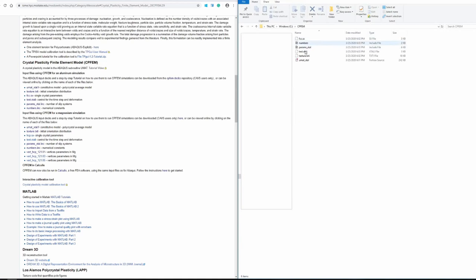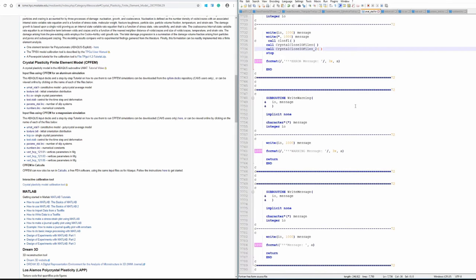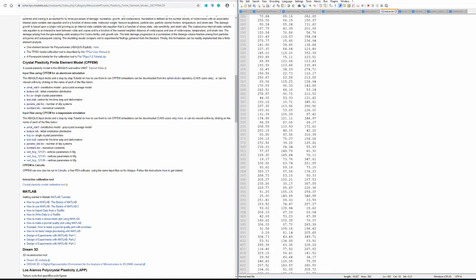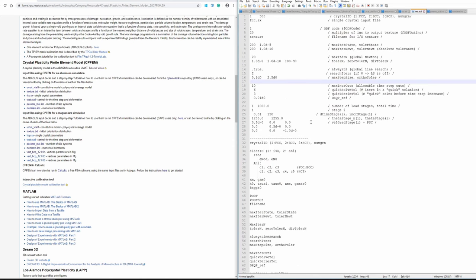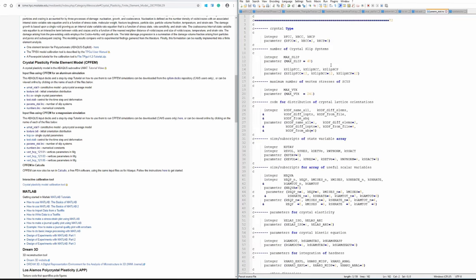Now we have all six files. Let me explain briefly what they are. This .for file is the UMAT—a very huge file with seven thousand lines. The texture file consists of Euler angles for different grain orientations. There are 500 grains and 500 pairs of Euler angles. This FCC file is your crystal structure—this example is for aluminum with FCC structure. You can see different slip systems and twin systems. Anisotropic elastic constants are also here. The test file is like an input file where you can choose how many grains you want or which crystal structure. The last two files are just parameters—you don't have to change anything in them.